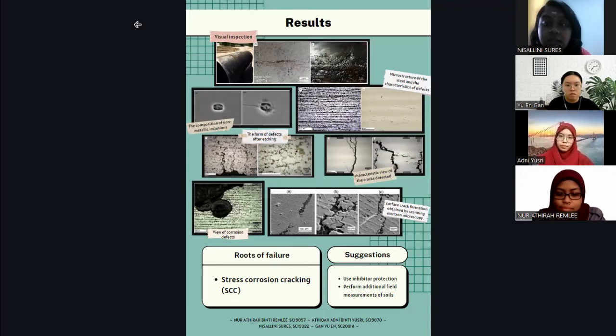Microstructural tests revealed that the studied steel exhibited a banded ferrite pearlite structure on the right, while on the left there is the presence of manganese sulfide inclusions in the steel, indicated by a high quantity of Mn and S in the composition of these inclusions as determined by EDX. The figure below describes the appearance of flaws after etching. This sort of fracture propagation implies that the SCC of pipeline steel is intergranular.